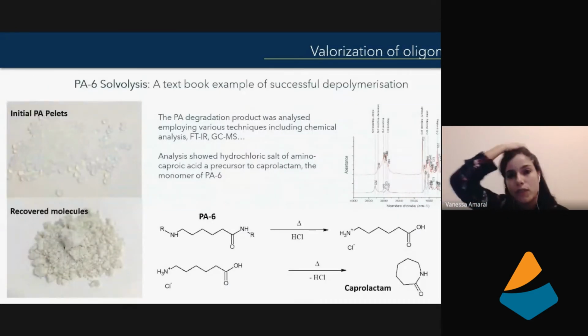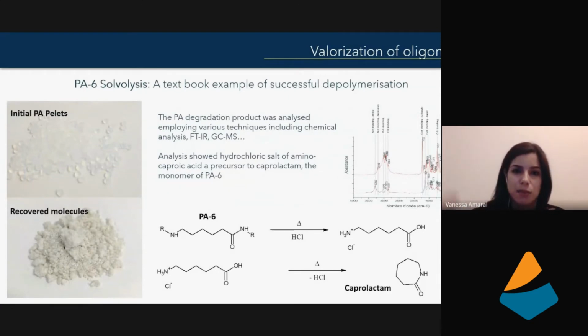And what happens with the oligomers? Here we can see a textbook example of how we can valorize these oligomers as a byproduct. Here is a case of polyamide 6. In order to avoid any contamination of the sizing of the carbon fibers, we use in this case only pellets of pure polyamide. We put it in the solvolysis, and then we recover this white powder.